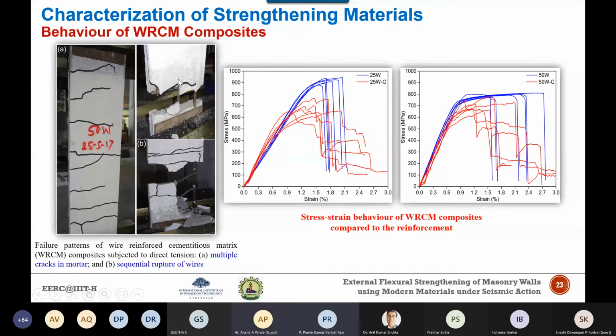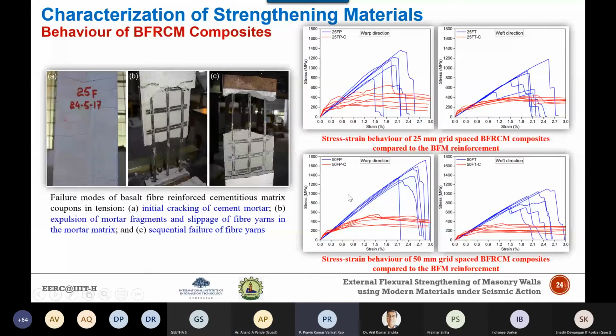Now, let's talk about the same thing with the fiber reinforced cementitious matrix. In the case of FRCM composites, in all the red curves compared to the blue curves, slippage occurred, with numerous cracks along the width distributed homogeneously over the entire specimen length. The majority of the specimens showed slippage between the mortar and the fiber mesh, except for one specimen where sequential rupture of the fiber yarns was observed. The slippage is mainly attributed to the low bond strength of the interface between the mortar and the fiber mesh, and therefore there is a significant reduction in all four stress strain curves. There is a significant reduction in the strength and stiffness of FRCM coupons compared to the dry fiber yarn, and this reduction can be attributed to the gradual slippage of the fibers.